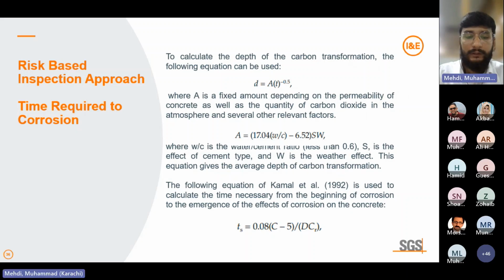Similarly, if we talk about the last equation, this is the equation of Kamal, and it is used to calculate the time necessary from the beginning of corrosion to the emergence of effects of the corrosion on the concrete. So CR is the corrosion rate, capital D is the bar diameter, and capital C here is the concrete cover thickness, where T_S, on the left side, is the time from the beginning of corrosion until the concrete cover falls down.